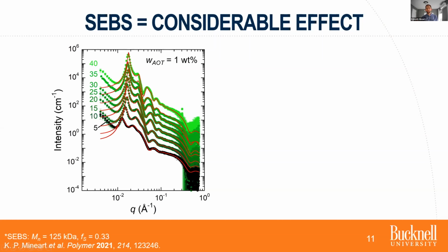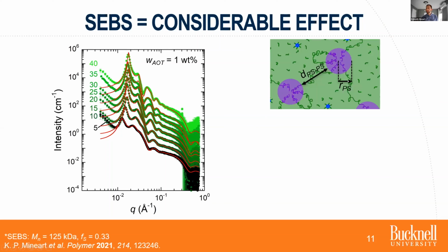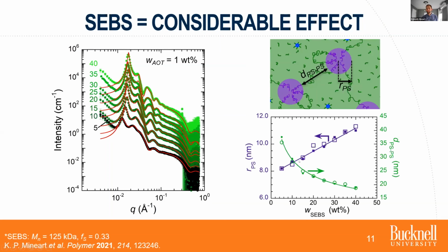And if we model these things, again, we see information about the AOT reverse micelles, but we also get these two geometric features quantitatively that I just mentioned. And we can plot those results and see exactly what I just mentioned. The radius of the polystyrene domains increases with triblock concentration. The spacing between them, the distance between surfaces of these crosslinks, decreases with copolymer concentration.